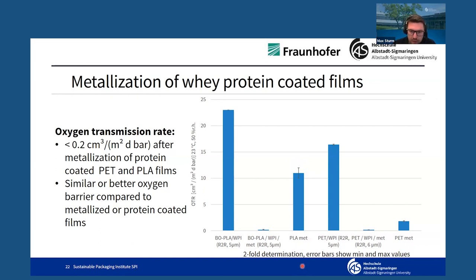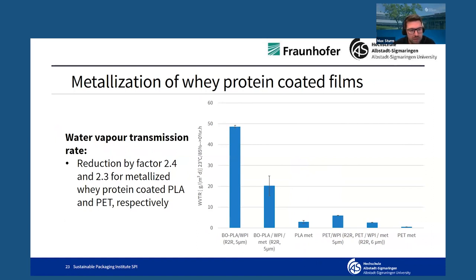Similarly, for PET, the OTR was reduced also below 0.2 cubic centimeters per square meter day and bar after the metallization. So similar results for both substrates. Also looking at the water vapor transmission rates, here there was a reduction due to the metallization application on the films. Here you can see also for reference the whey protein coated PLA from the pilot scale, which has then been metallized, with a reduction from about 50 to 20 grams per square meter a day. And also for PET, about a 2.3-fold reduction from 5 to about 2 grams per square meter and day for the water vapor transmission rate.